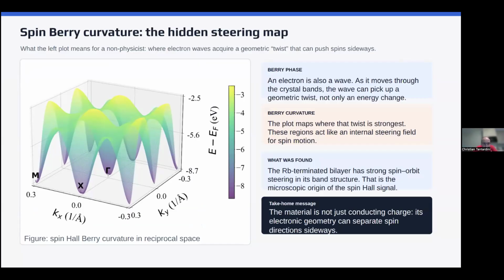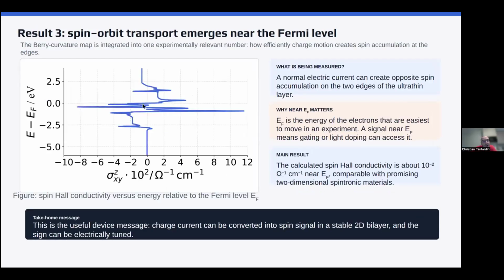And the Berry phase gives me the movement of this electron inside the material, specifically inside the K space. So the electronic geometry can separate spin direction sideways, and this is important to remember. Specifically, the last result that was the most interesting for us is that we have this high spin Hall conductivity, in the order of other compounds previously seen in the literature, making this a two-dimensional spintronic material that works with hole doping or gating. If we go below, the chemical potential starts to be below zero, we get an opposite signal and we have a transition of the spin Hall conductivity.